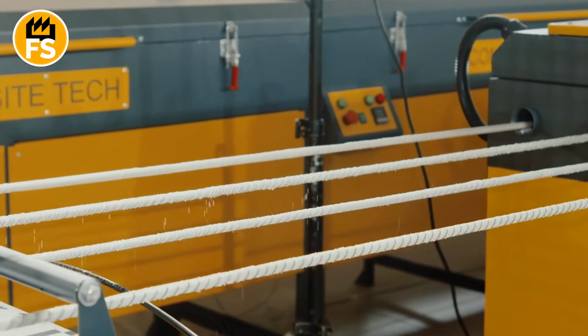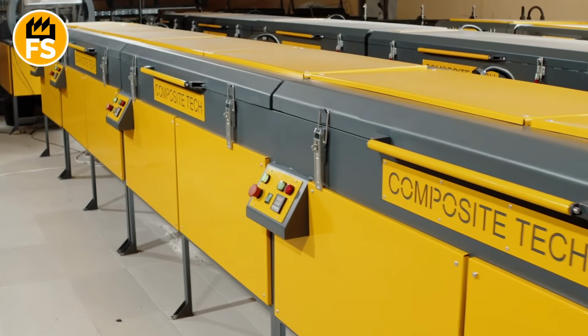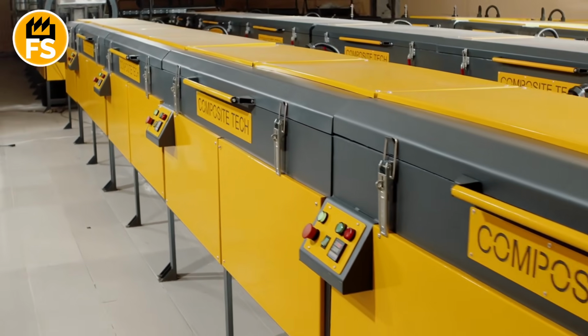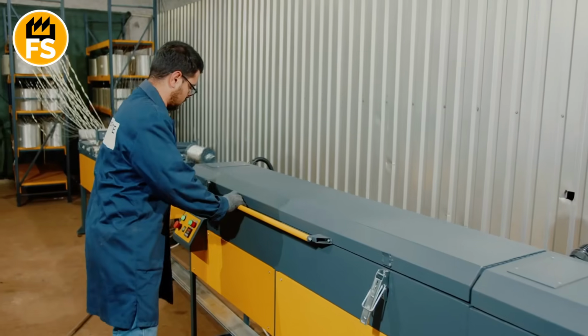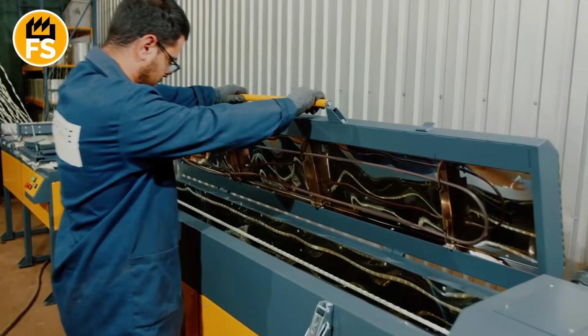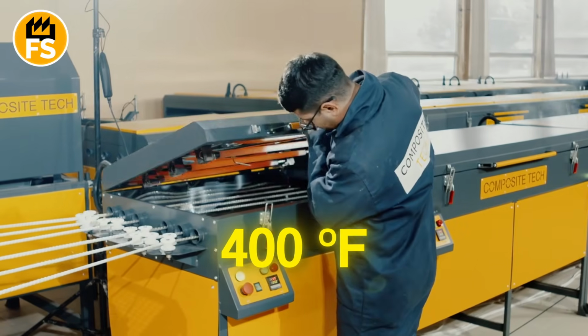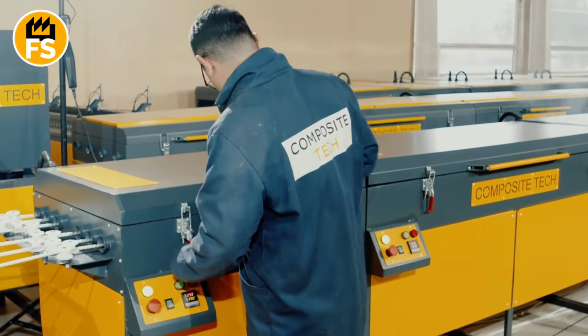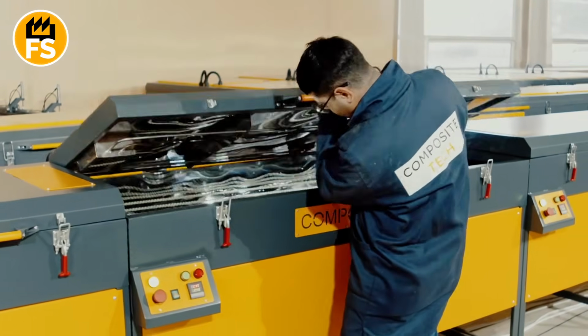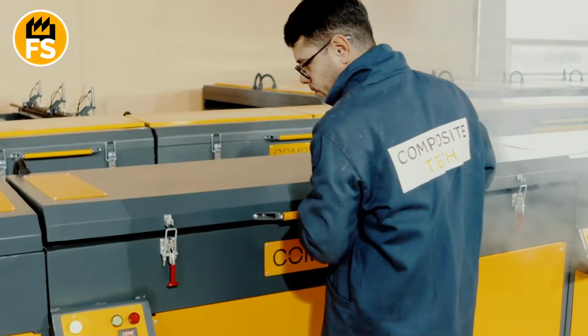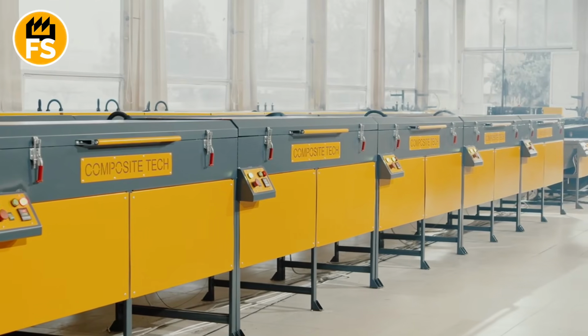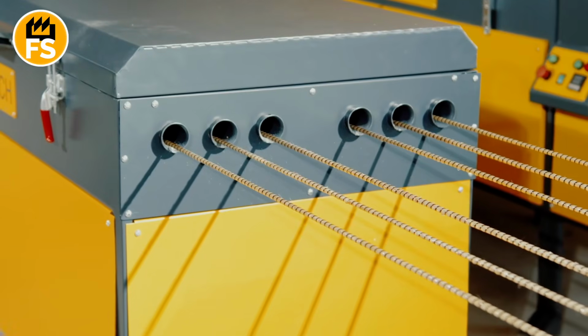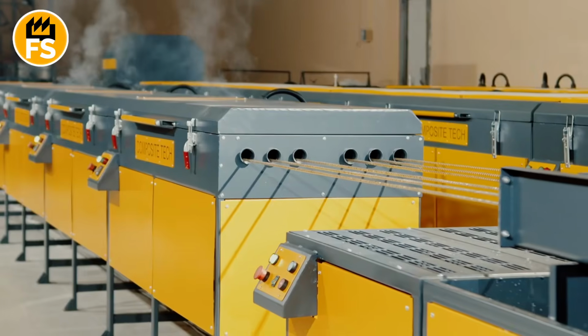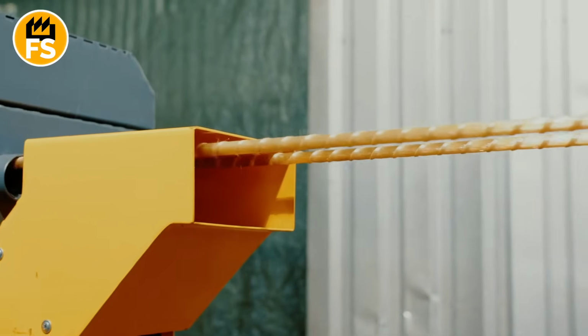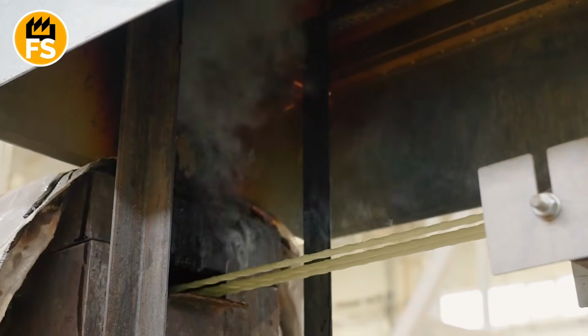The formed and wrapped rod enters the longest part of the machine, the curing tunnel, or polymerization furnace. This is a long chamber that can stretch for tens of feet, inside which a high temperature is maintained, usually 400 Fahrenheit. Here, the final transformation takes place. This is not just drying. Under the influence of heat, the resin molecules begin to actively connect with each other, forming a strong, rigid, three-dimensional network. The liquid, sticky syrup turns into an extremely strong and hard composite material, which firmly binds millions of glass fibers into a single monolith.